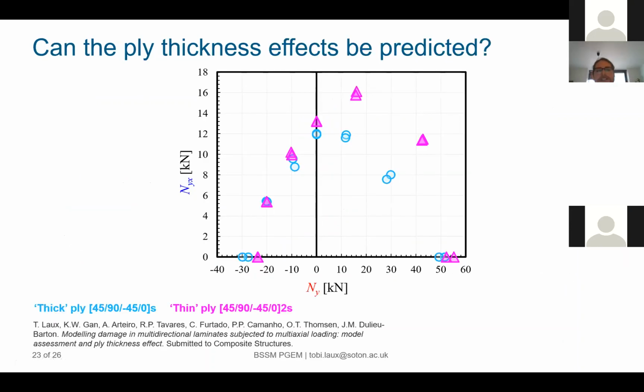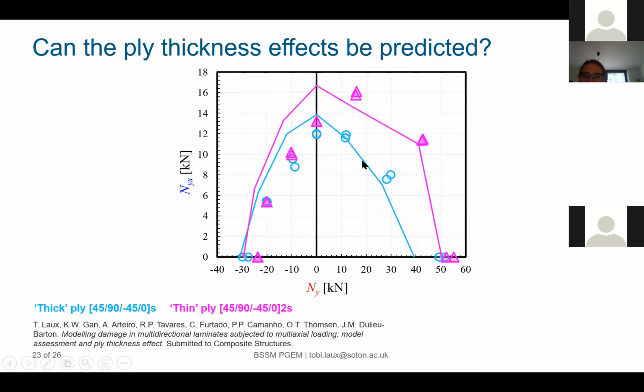So that's promising. So can the strength of this actually be predicted? Well, so this is the prediction of the thick ply. This is the prediction of the thin ply. So what we can see here certainly is we do a pretty okay job for tension shear. In compression shear, there seems to be an over prediction of the strength for all these cases. But overall, the mean relative error is 15%. That may sound like a lot for some of you, but you have to consider that for a uniaxial open hole test in the open literature, the mean relative error is 10%. So actually, it's not so bad considering the additional complexity.